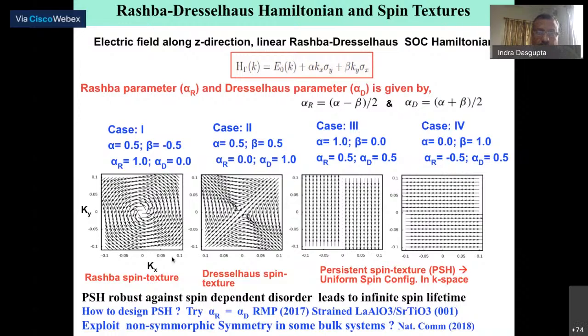Well, so as I was trying to tell you, if you choose a system where the electric field is along the z direction, then you have a linear Rashba Dresselhaus SOC, and the most general Hamiltonian can be written the way it is written out here. This is the most general Rashba Dresselhaus Hamiltonian, and alpha minus beta essentially gives you the Rashba parameter, and alpha plus beta essentially gives you the Dresselhaus parameter. A system usually can have both finite alpha and beta, and as a consequence, it can have partially Rashba kind of coupling, partially Dresselhaus kind of coupling, and depending on the system, either of them can dominate.